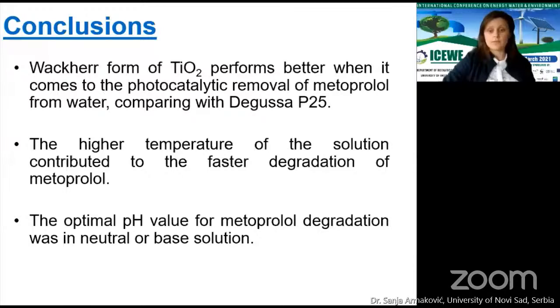It has been found that the Wacker form of titanium dioxide performs better when it comes to the photocatalytic removal of metoprolol from water. In the case of both photocatalysts, the higher temperature contributed to the faster degradation of metoprolol. The initial pH of the solution has proven to be very important to photocatalytic degradation of metoprolol. The most efficient degradation was achieved at 7 and 9, when the substance is positively and the catalyst negatively charged.